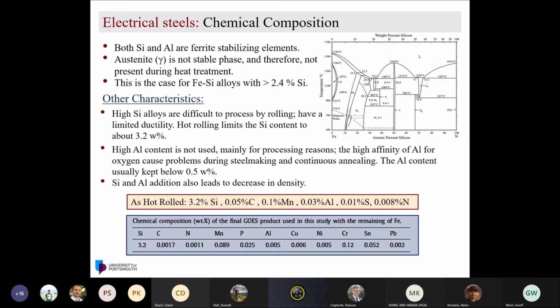That's very important, because I'm opening the window of heat treatment without transforming the steel to austenite. It remains ferrite, and I can do the heat treatment. That's one of the reasons silicon steel can be heat treated at 1200 degrees Celsius and even more, because you are not facing austenite formation.